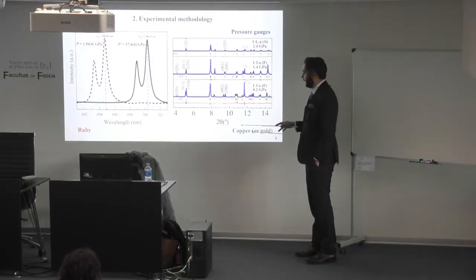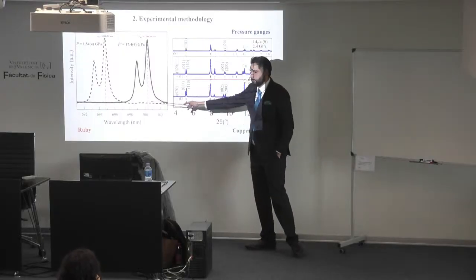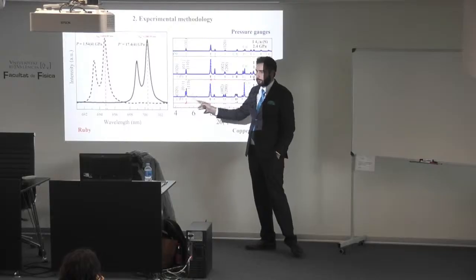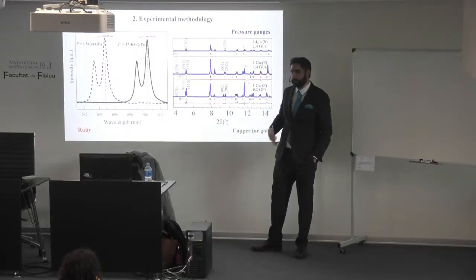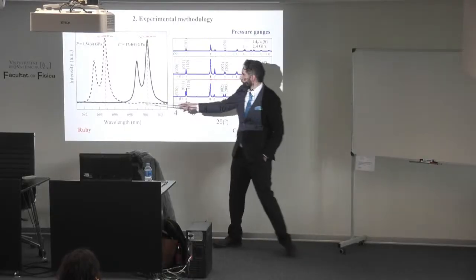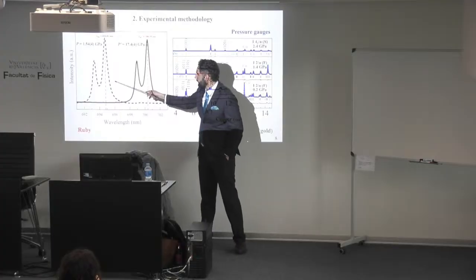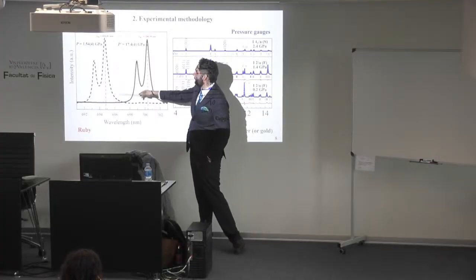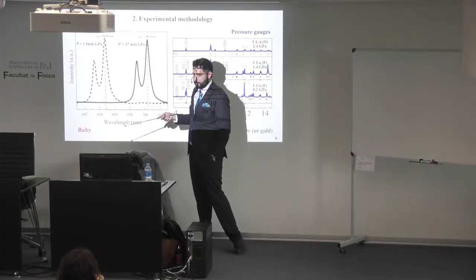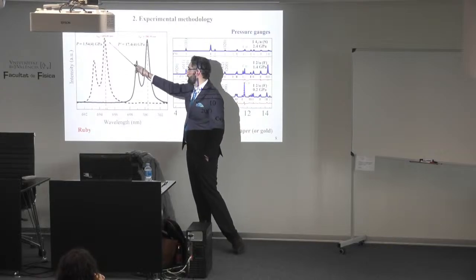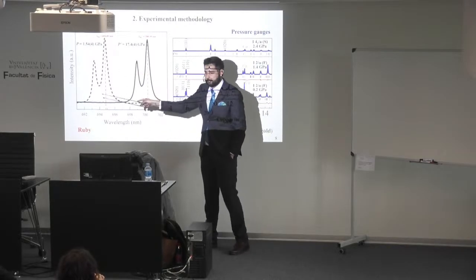As far as we can, we try to do the ruby method. If we point some laser at the ruby, we excite the luminescence. We see this couple of peaks. This principal peak, R1, is the most characterized, so we use this in order to check the pressure inside.